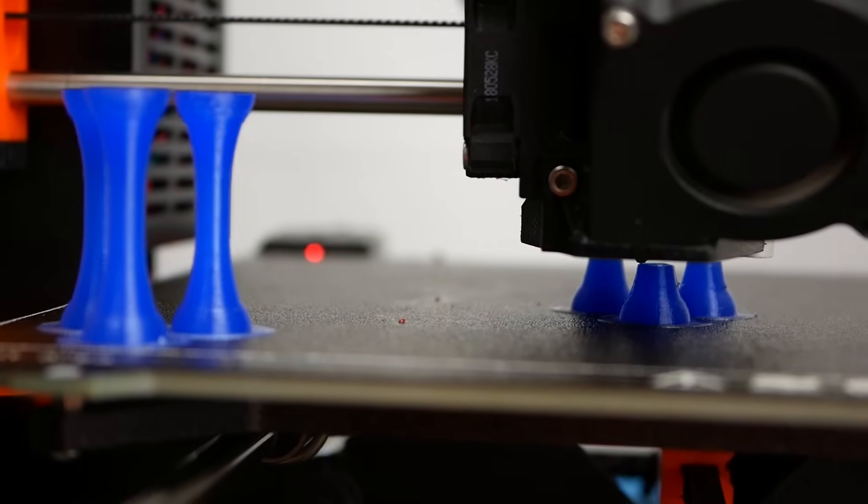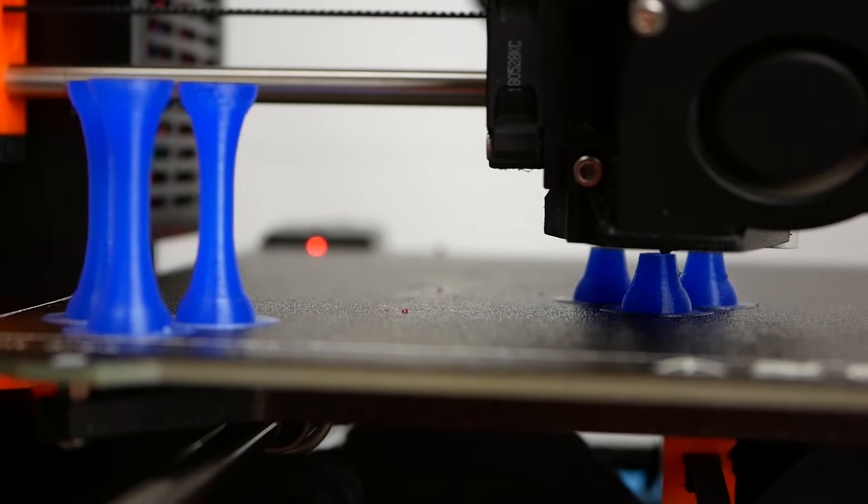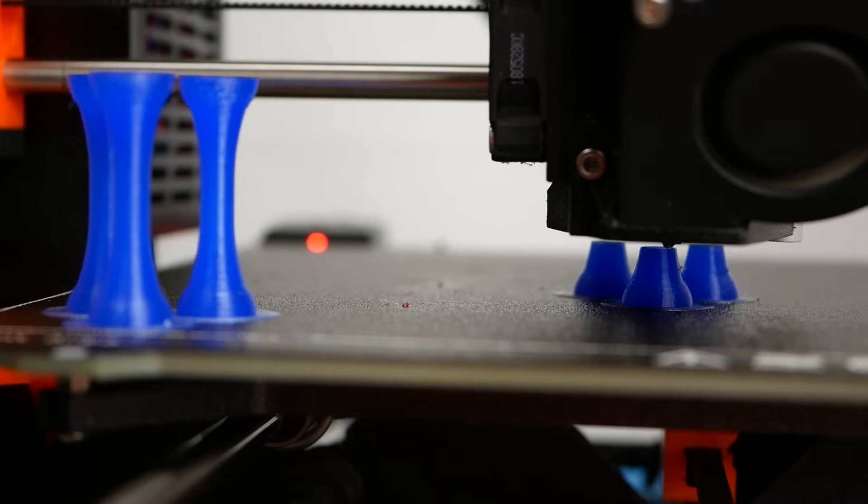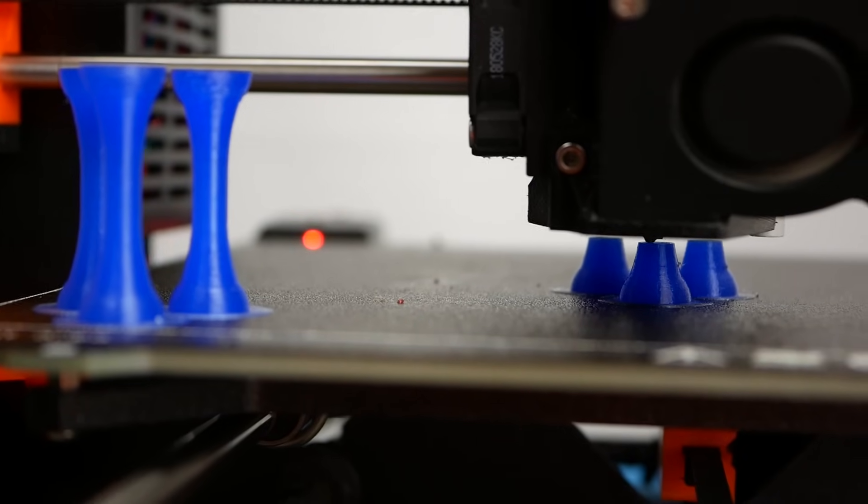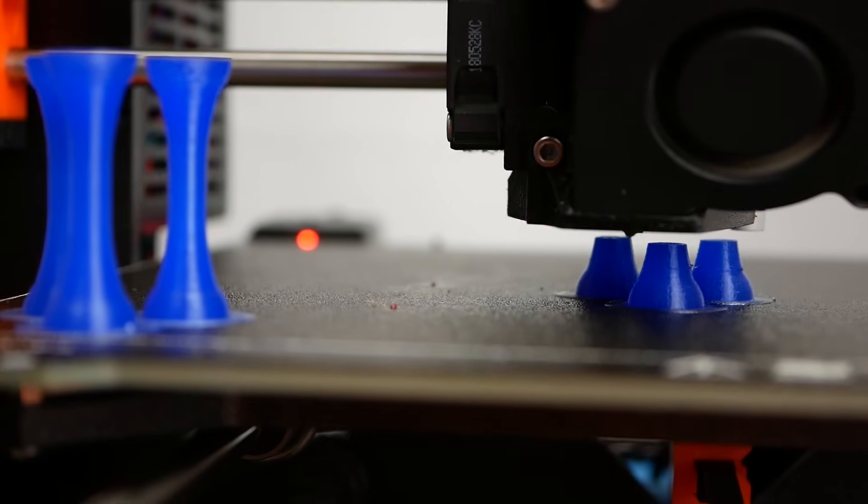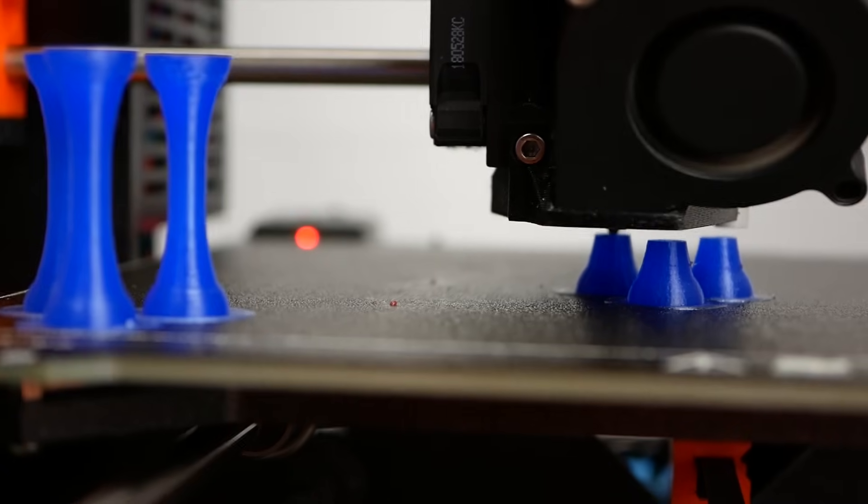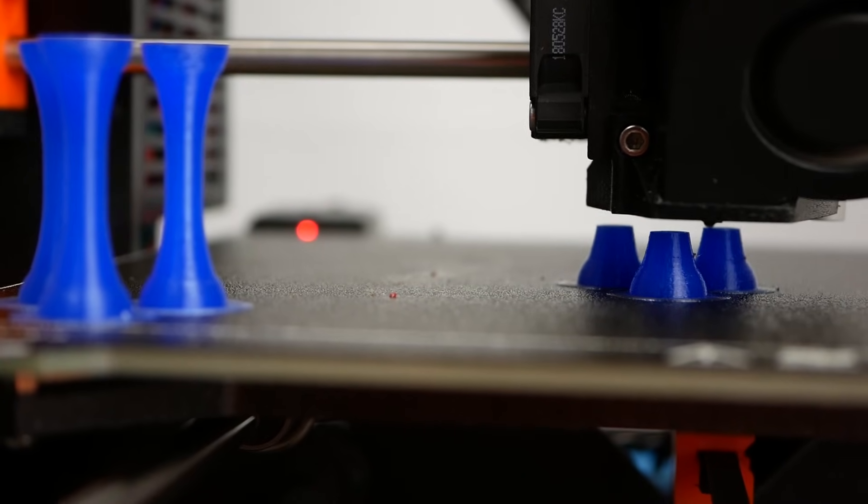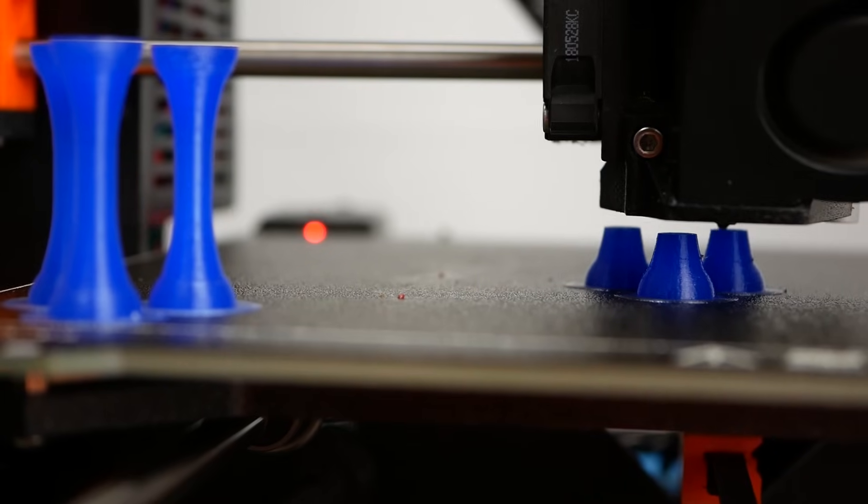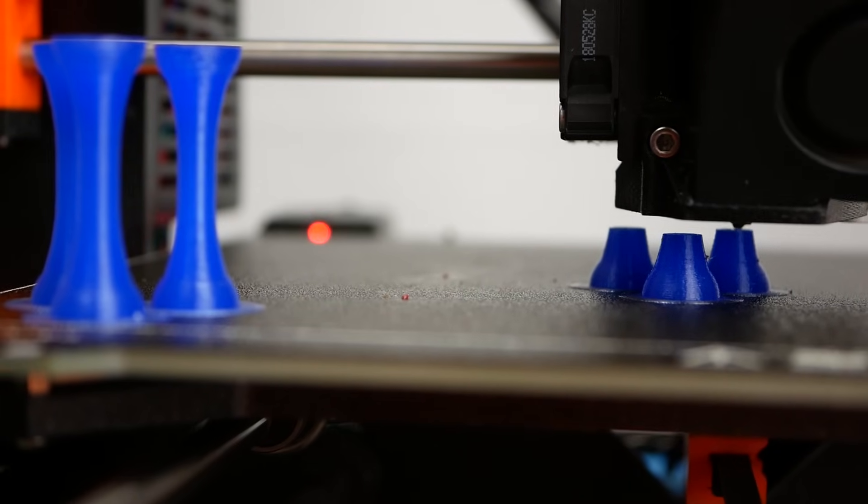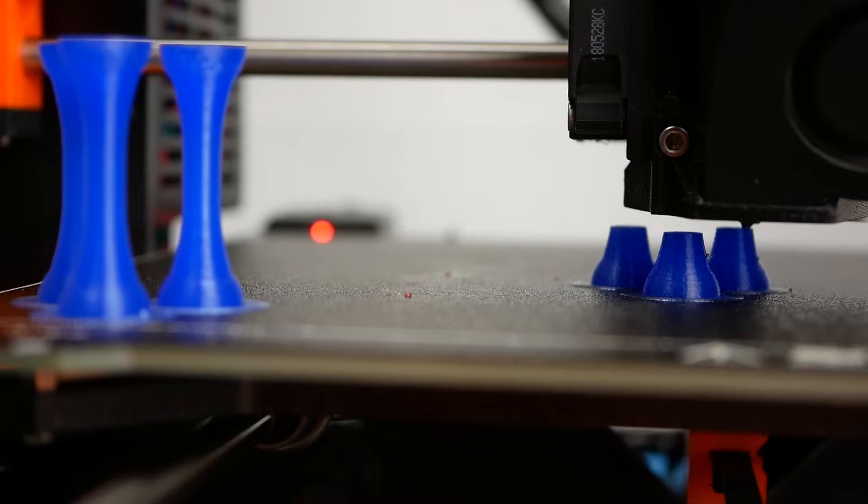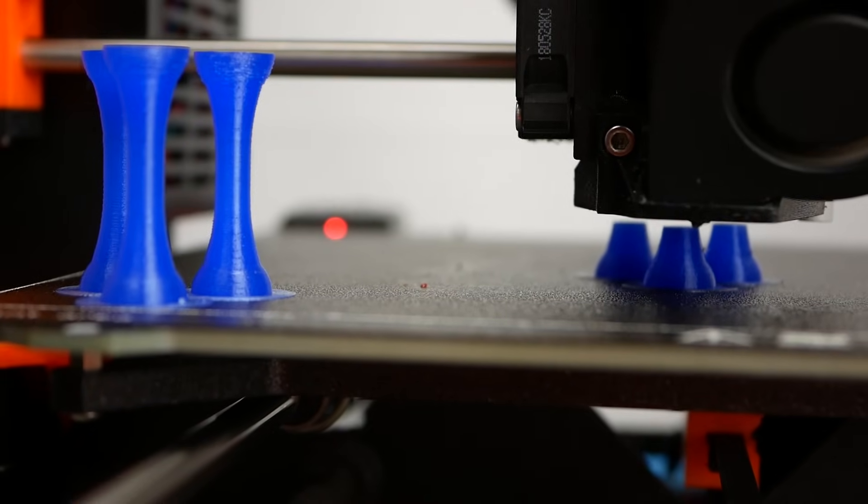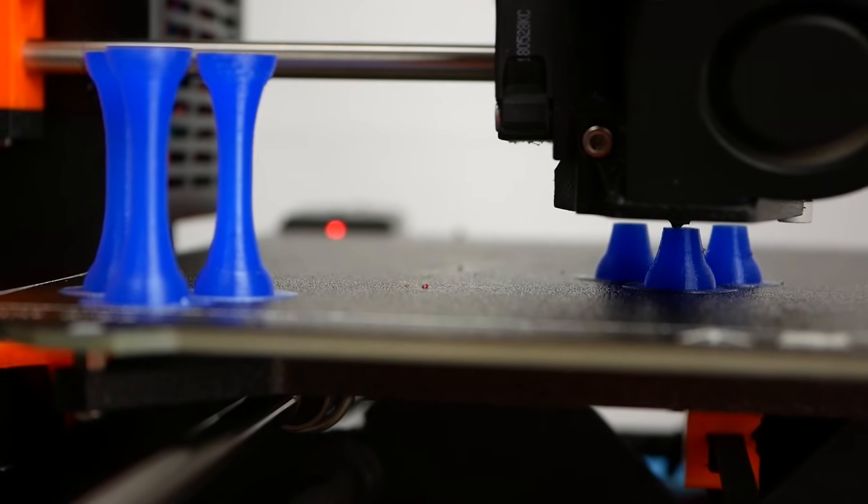Secondly, the material should be printed with less than full cooling fan because this decreases strength but the print quality as we will see in a minute still remains nice at settings below 50%. For both PETG and PLA we have seen that the layer adhesion is always significantly lower than the base material strength, still we can influence the adhesion with the amount of cooling we use and less is usually better.